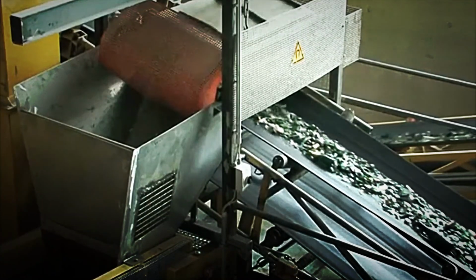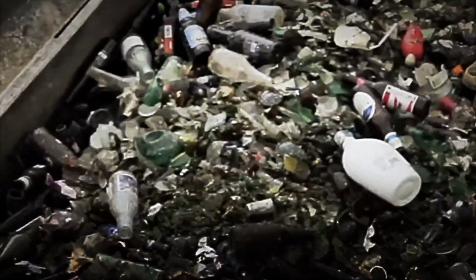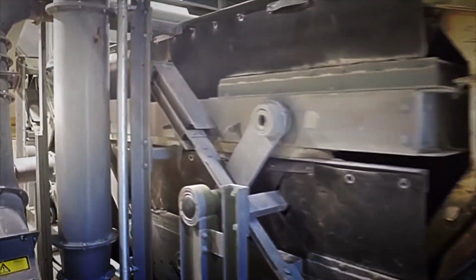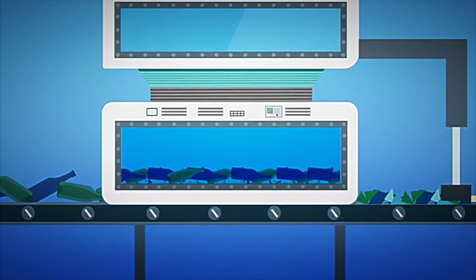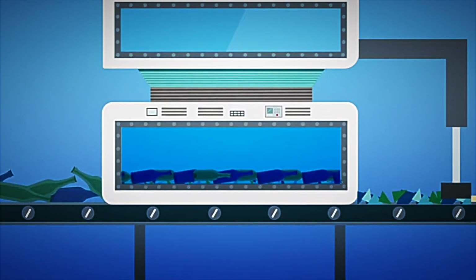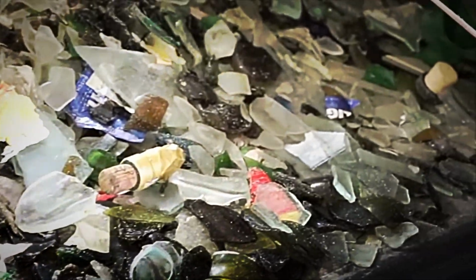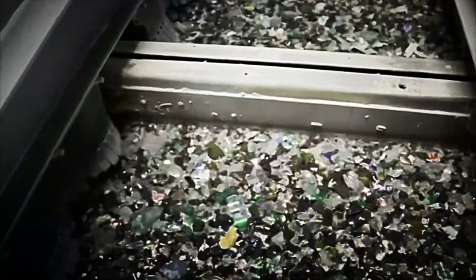For the final marbles to have transparency, shine, and structural strength, the glass must reach a nearly perfect level of cleanliness. Once clean, the glass moves to the crushing phase. The containers are fed into industrial hammer crushers, where they repeatedly collide against rotating steel arms at high speed. In just seconds, the bottles and jars are completely broken, turning into millions of bright and sharp fragments known as cullet. This material is ideal for recycling because, having been previously melted, it melts much faster than virgin raw materials, significantly reducing the energy consumption of the melting process. At this point, the waste is no longer considered trash and becomes industrial raw material.